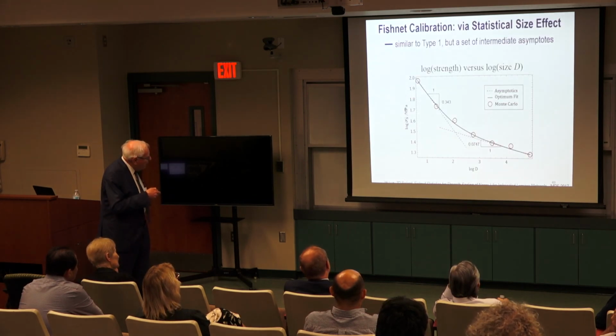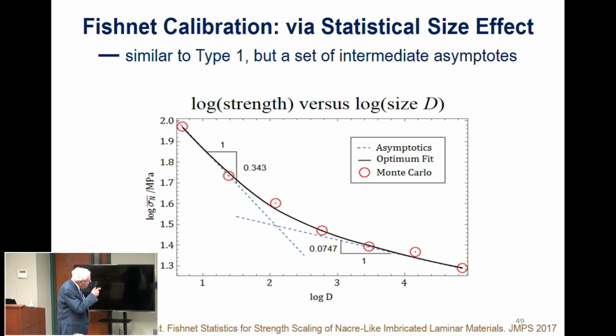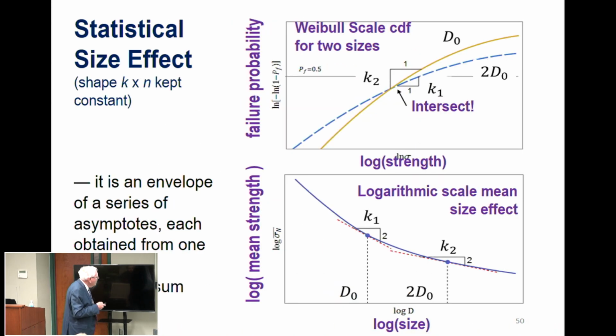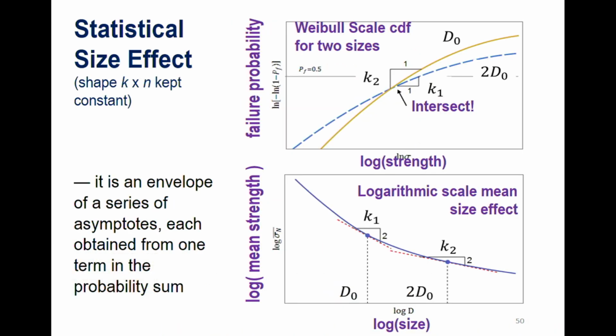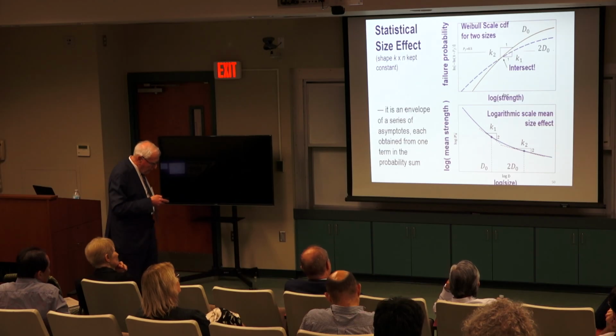Now this is a size effect that we computed. It's similar to the type one that I showed at the beginning, but it is somewhat different. For brittle fishnet, it's actually a curve which is an envelope of asymptotes which corresponds to 1 link, 2 links, and so forth being failed before maximum load. What is interesting is that as you change the size, distributions change or rotate about one point here, generally. And this corresponds in the size effect curve to transitions from one asymptote to the other.